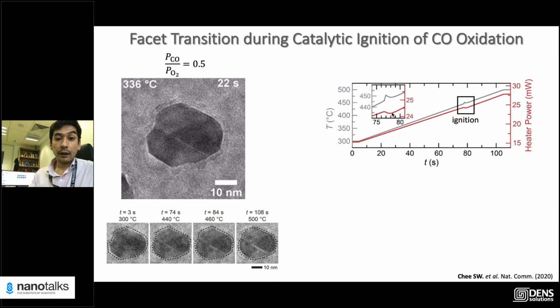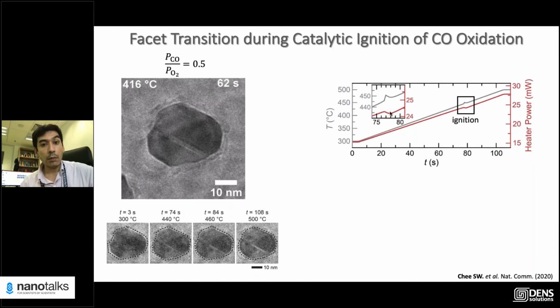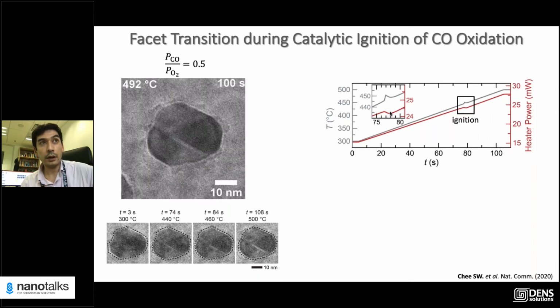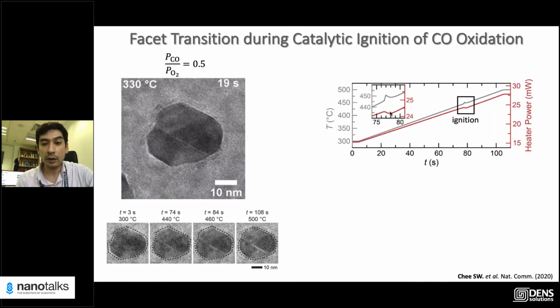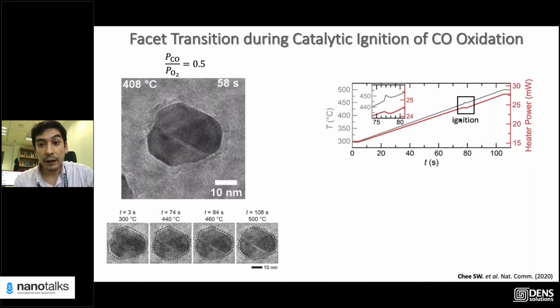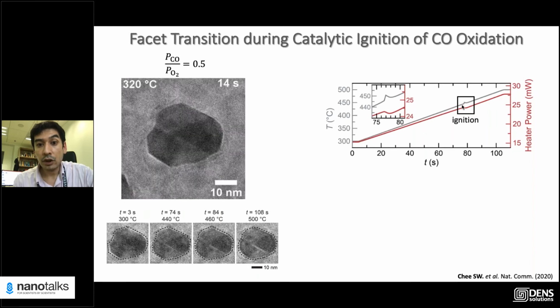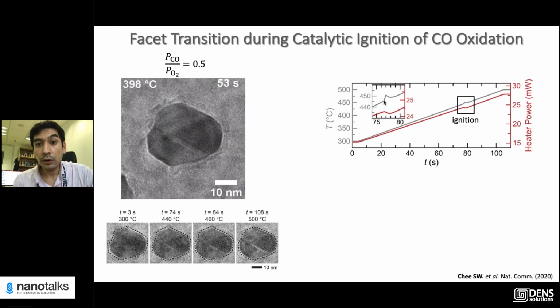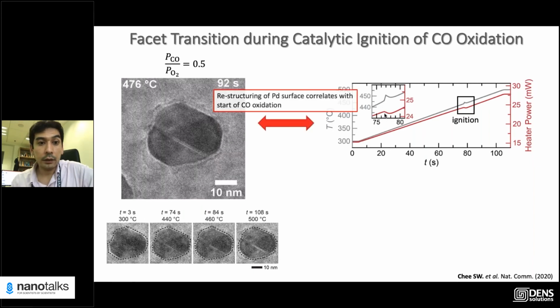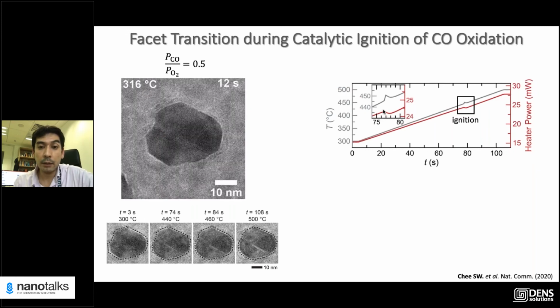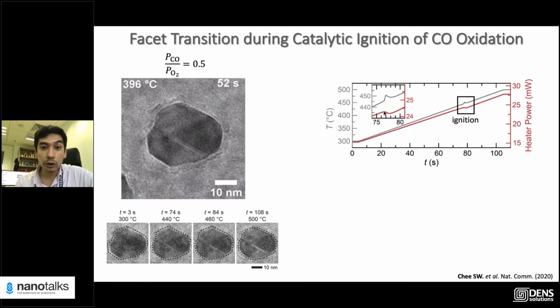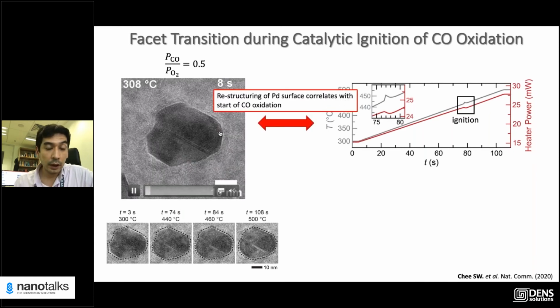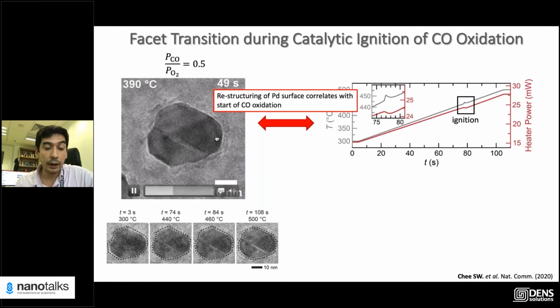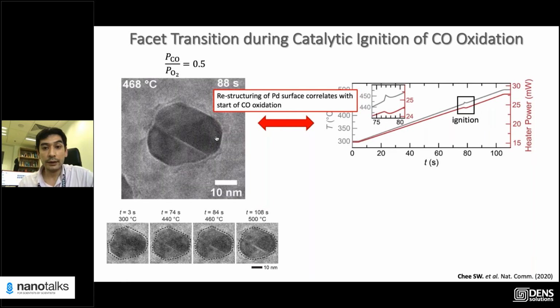And quite interestingly, while you're monitoring, not only can you monitor the CO2 production or the products using the mass spec, but you can also monitor what the heater is doing. And what we see with the heater is, as we ramp up the temperature, once we hit this 450 or so, you see a sudden drop in the power that's supplied to the heater, right? So this point corresponds with the structural change that occurs with the nanoparticle. So this restructuring and the transition of the particle really coincide.